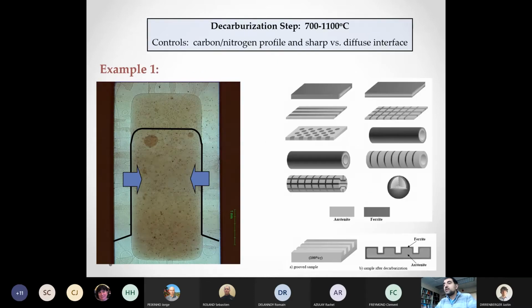So here's an example of the first case where we have a sharp interface, and you could see how there is a ferrite layer on the outside, and then we have martensite on the inside, and they're separated by a sharp interface. And we could imagine many different shapes of this two-phase material that we can create by applying a mask. So we played a little bit with copper-based masks. They're very effective at blocking the carbon diffusion, and one can try to create different shapes, and they're very interesting. But the main disadvantage we had with this approach is these very large ferrite grains at the surface, which become a site for the crack propagation. So although this is interesting, it looks appealing, in reality, it didn't have very good mechanical properties in most cases.